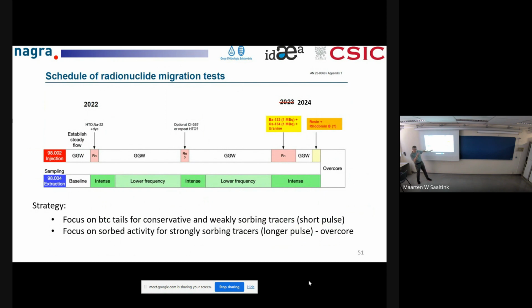We do the pulse, which is very short, and then we inject water for a long time, and we want to look at the tails of those breakthrough curves and try to interpret that. That's already being done, and I'll show you the results. The second part has not started. It should have started in '23, '24, and will happen later this year. So we'll inject the strongly sorbing tracers, a 21-day pulse.